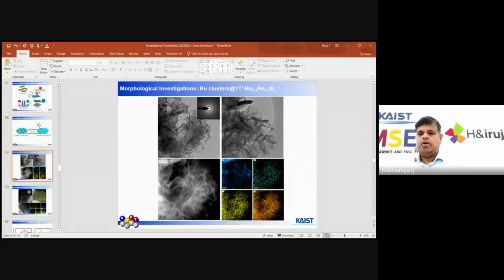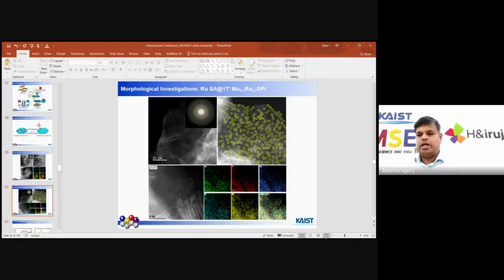You can see before, this is the cluster. The metal nanoparticle cluster is observed, and this cluster can be clearly observed by the color mapping and HRTEM analysis. So after the cluster, we successfully transformed it into single atoms. You can see there is no cluster observed. Yes, our strategy may be helpful to make single atoms with high loading. I rounded up the single atom of ruthenium over the thin chalcogenide networks, and you can see the ruthenium single atoms are homogeneously distributed throughout the area of the chalcogenide.